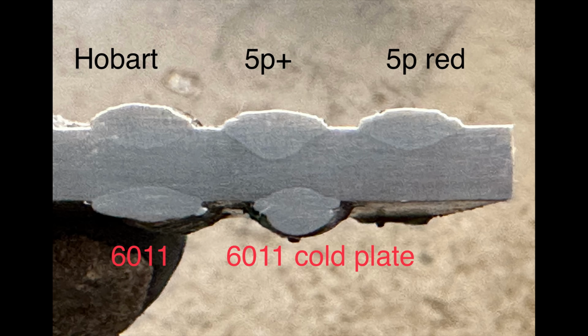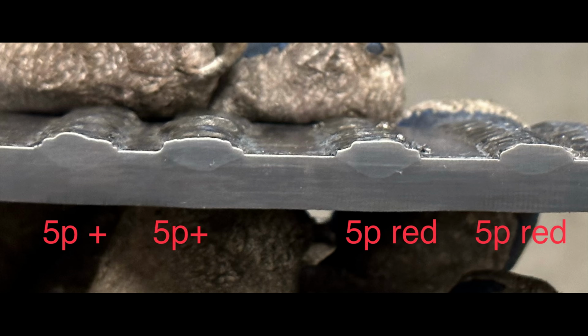And two, the rod doesn't penetrate, generally speaking, as much as 6010 does. Now here we have a shootout between red and 5P Plus. As you can see, that one red weld has deeper penetration than the others. It's all dependent on where you cut the plate. But overall, the penetration's looking real good.